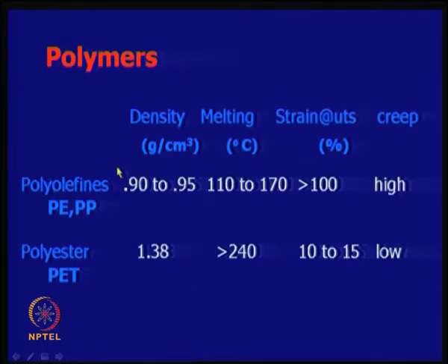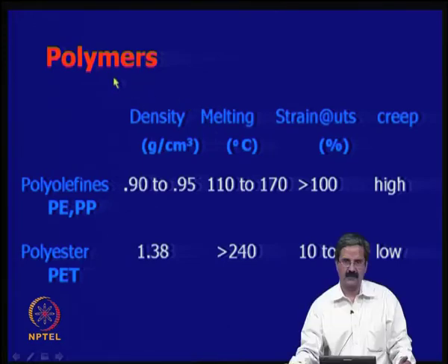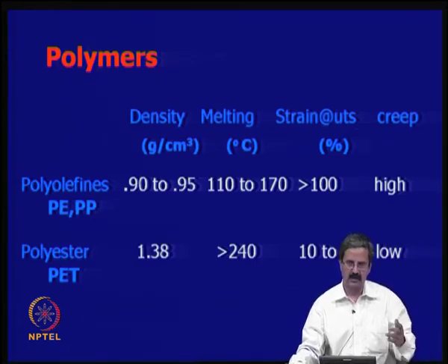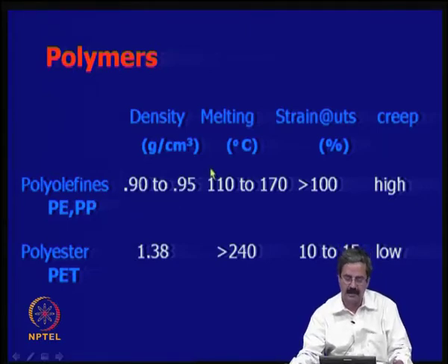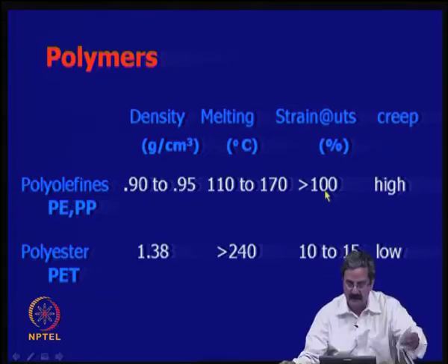Another piece of information we need is that, as I just mentioned, these are all polymeric materials combined by CH bonds, carbon-hydrogen bonds. It is a molecular chain of carbon and hydrogen, and depending on the manufacturing process they can have different properties. For example, polyethylene and polypropylene belong to the family of polyolefins, with densities of 0.9 to 0.95 and a melting point of 110 to 170 degrees. They are stretchable, for example a geotextile.